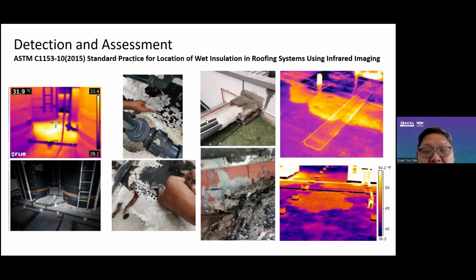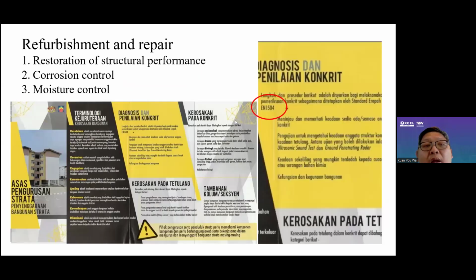So this is some of the waterproofing coating membrane that I checked using infrared imaging. And of course, whatever the repair or diagnosis, KPKT recommends EN 1504. So in this system, it emphasizes not only the restoration of structural performance, we also need to control the corrosion before we do the moisture control. So these are the 3 steps according to EN 1504 for concrete repair and protection.